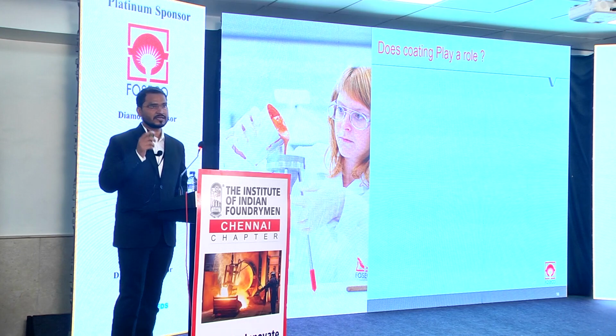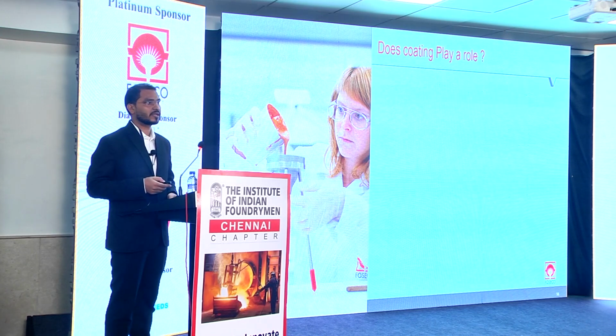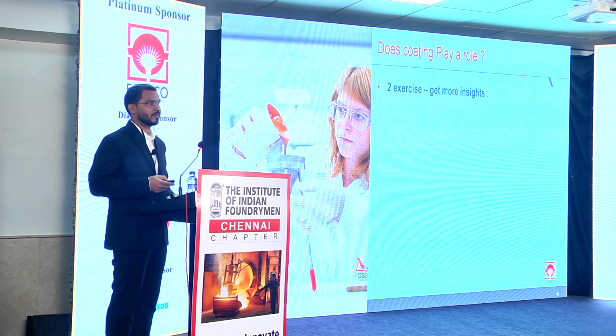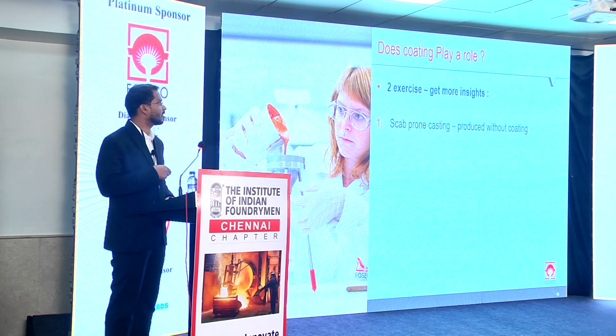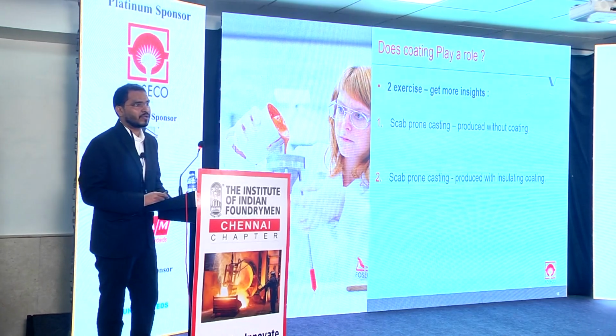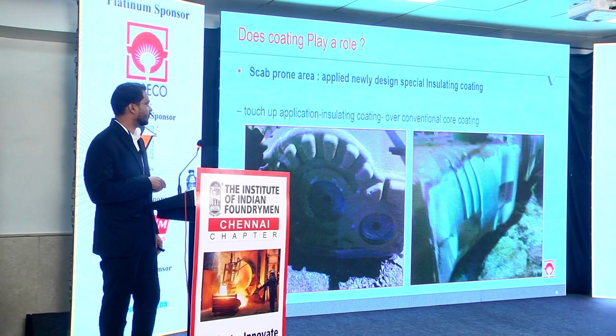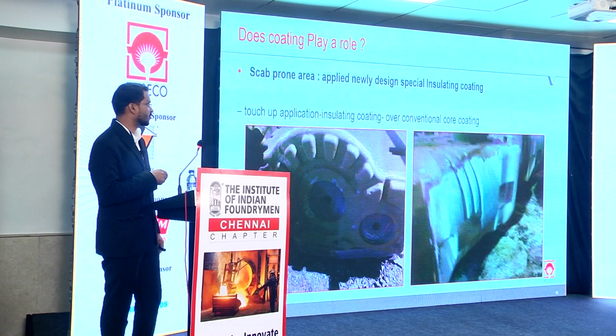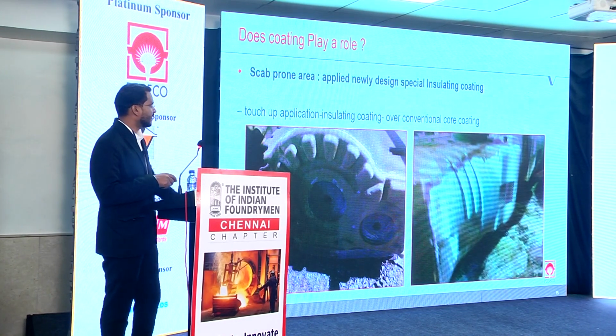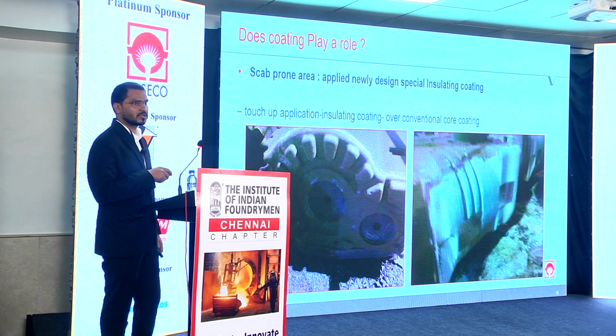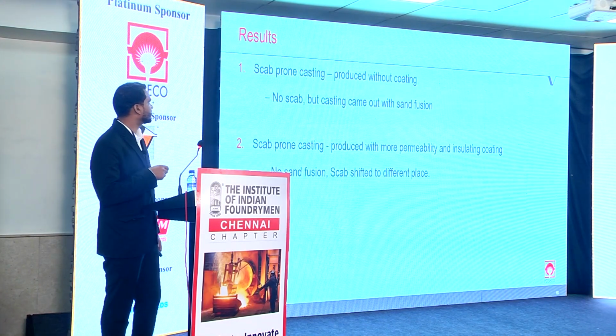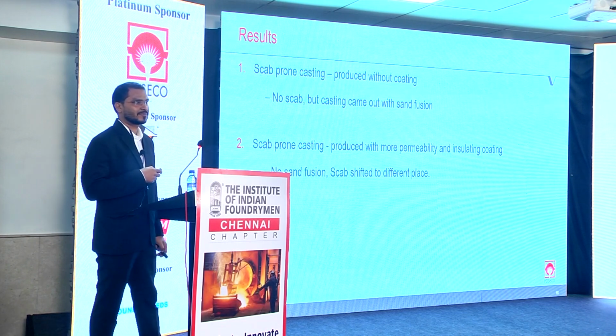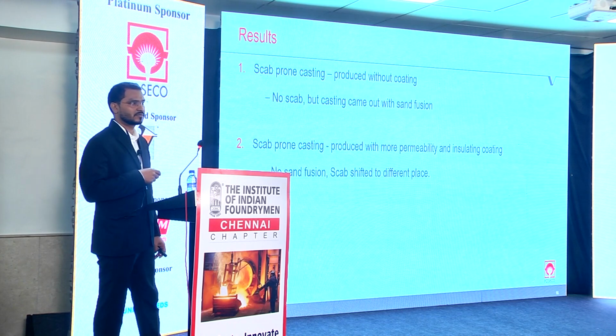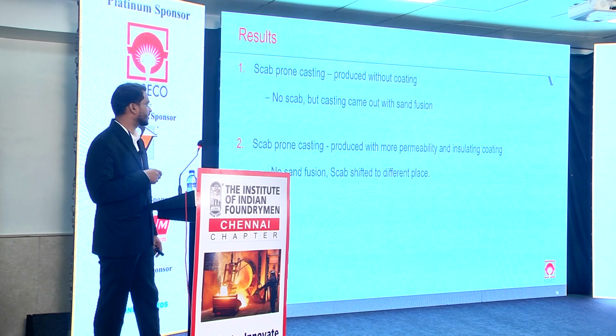So when we started working together with the foundry, we suggested: let us do an experiment, do one casting without coating and one casting with a special coating. We have some insulating coating, and we tried it. These are the images of two different castings. On the left side, the casting was poured without coating application, and the other casting had that special coating applied. If you see the casting results, the first casting had no scab, but it came out with sand fusion, and the second casting did not have sand fusion, but the scab shifted to other areas. So we understood that there is a role of coating, and coating can play a major role here.